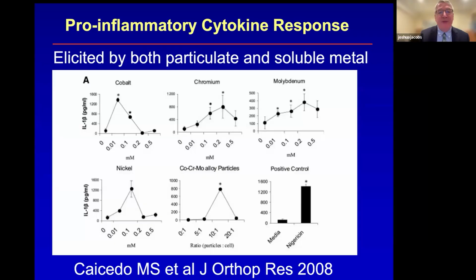We know, through a number of studies we've done in our lab and elsewhere, that at the right concentration, cobalt, chrome, molybdenum ions, and we studied chlorides here, can elicit pro-inflammatory cytokines. This is interleukin-1 beta, which is known to be a very pro-inflammatory cytokine that we study because it could be associated with periprosthetic osteolysis or bone loss, inflammatory bone loss.